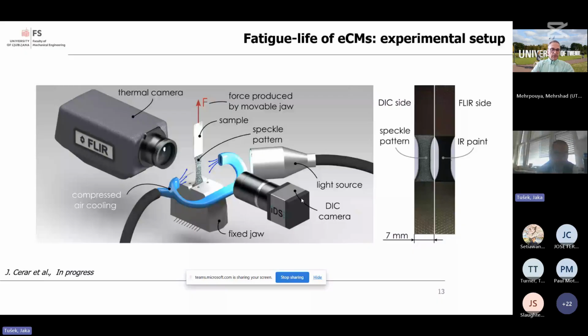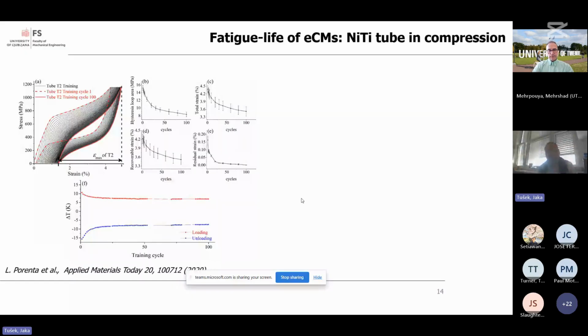We have first studied fatigue in nickel titanium tubes in compression, but before we do any characterization, we first perform so-called mechanical stabilization, or training, of the material, where in the first 100 cycles, for example, there is quite significant degradation of both the elastocaloric effect and the superelasticity. But after roughly 100 cycles, the response is stabilized and reproducible, which is obviously crucial for elastocaloric devices.